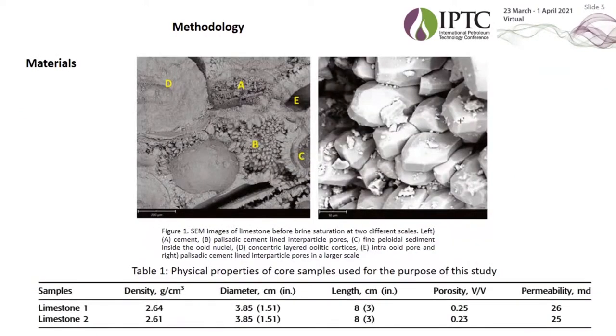The Sommerard limestone from Eastern France was used in the study. This limestone is a heterogeneous rock with different percentages of calcite and dolomite based on the X-ray diffraction result obtained. The microstructure of the limestone as it appears in scanning electron microscope SEM images is complicated and characterized by intraoolitic pores, sediment inside the ooid nuclei, and palisadic cement lined interparticle pores and cements. Their petrophysical properties such as porosity and permeability were measured before injection as given in table 1.